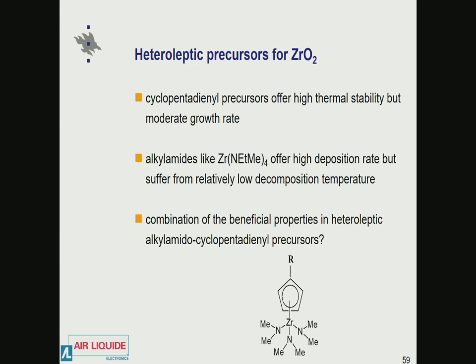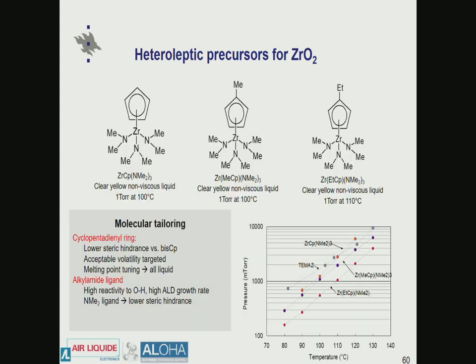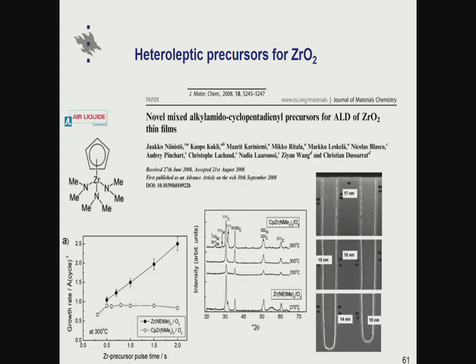And Air Liquide was synthesizing a range of this kind of complexes where there is one cyclopentadienyl with a substituent or without a substituent, and then three alkylamide ligands, and these are the simplest examples shown here, also with reasonably good volatility. We then tested the simplest of these, so unsubstituted cyclopentadiene here, and these three dimethylamine ligands, and we compared that against the alkylamide alone.